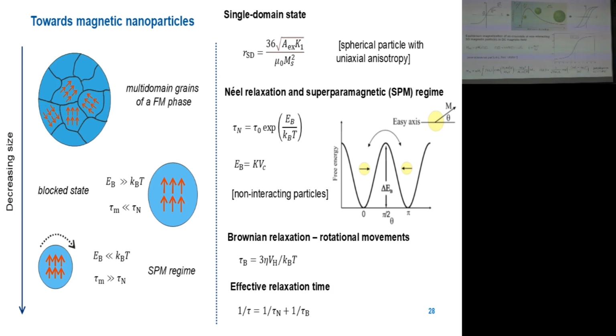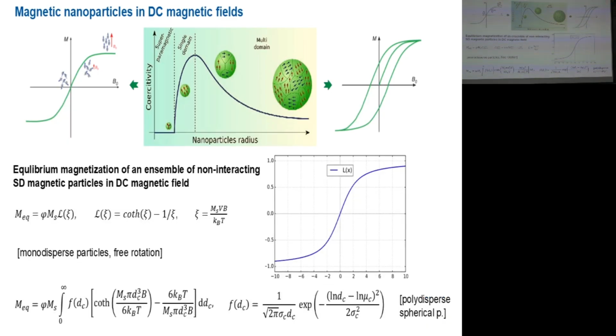So this was the introduction. And now, how is it with the magnetization of the sample? Let's see the magnetic response of a typical ferromagnet in a DC magnetic field. If you measure the sample on your magnetometer, and if you analyze the hysteresis loop, you will see something like this. A typical loop of a ferromagnet with multi-domain structure. If you prepare nanoparticles of the same material with a size small enough, you will not see the loop, but you will measure some anhysteretic response like this. And you may think that it is superparamagnetic. It needn't be superparamagnetic. It can also still be blocked, but just the coercivity might be very, very low. So you should consider also a situation that it might still be a really blocked sample, but very magnetically soft.